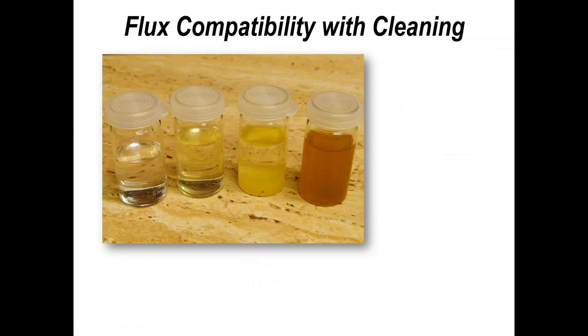Solubility will also speed up the process — the time taken to get to the level of cleanliness you require. What I tend to do is take some sample flux material and put it into a cleaning solution and look for it to go truly into solution. Any cleaning process can literally blow residues off with the force of solvent or water, but that's not real cleaning. Cleaning is dissolution — residues going into solution — and then replacing that with cleaner levels of cleaning solution prior to the drying phase. That is the true essence of cleaning.